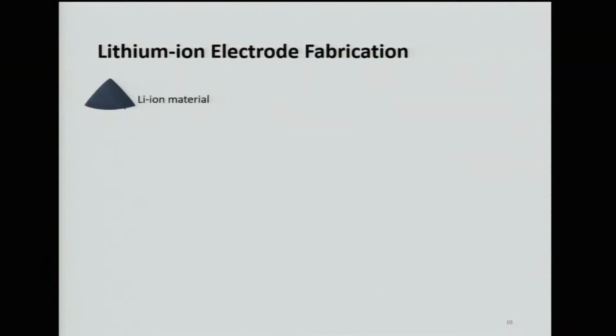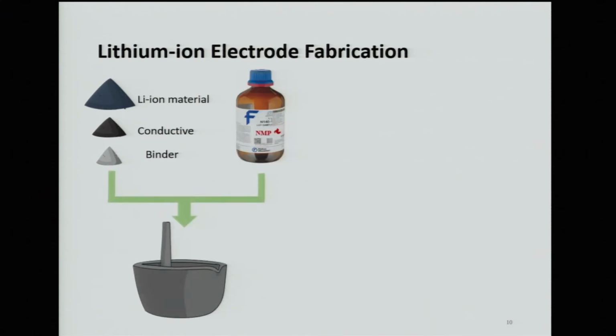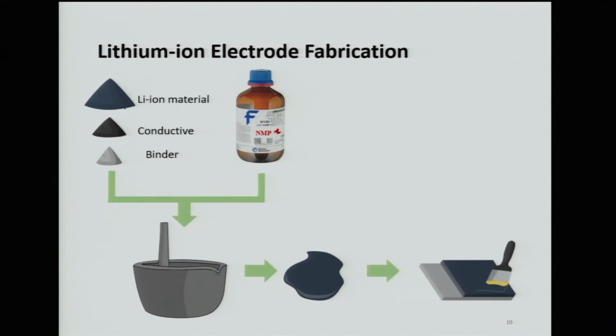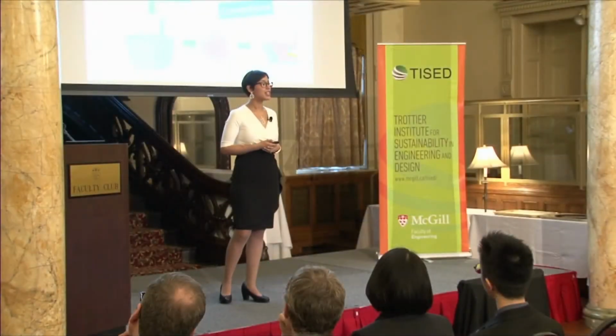The first material we put in there is the lithium-ion material. Now, these materials tend to have really poor conductivity, so we can improve this by adding conductive material. And this is typically done by adding a small amount of carbon. We also add a binder to hold everything together. These powders are mixed with a liquid called NMP. This gives us a slurry, just like paint. And just like paint, we can then paint it onto a metal surface. This is the conventional fabrication technique for lithium-ion electrodes that we use in industry.